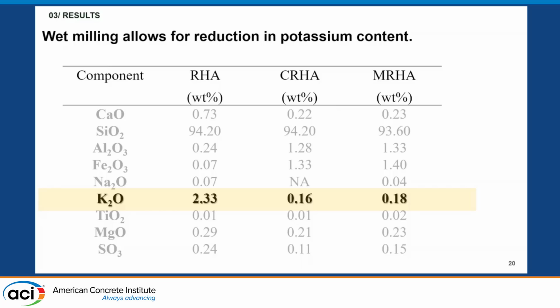The only note that I will say, which I did not highlight here as much, is that there can be potential for contamination depending on your mill type, and so that's another factor to consider, like which ball media you're using, which ours is corundum, which might be explaining why there's a bit of an increase in the alumina, and as well as we have a steel mill, which can explain some of that potential contamination.